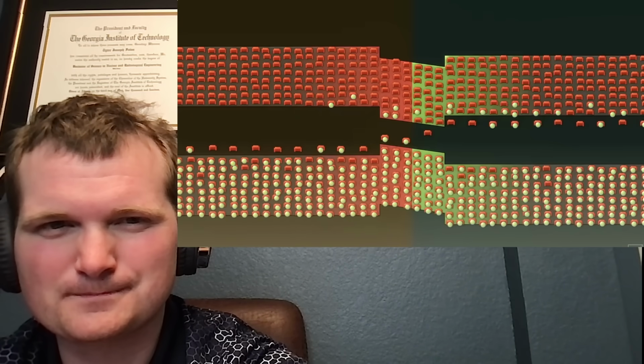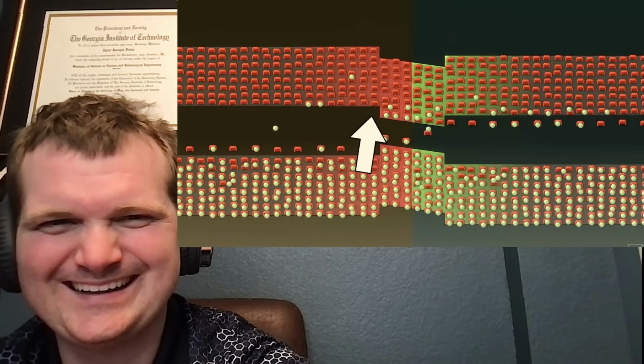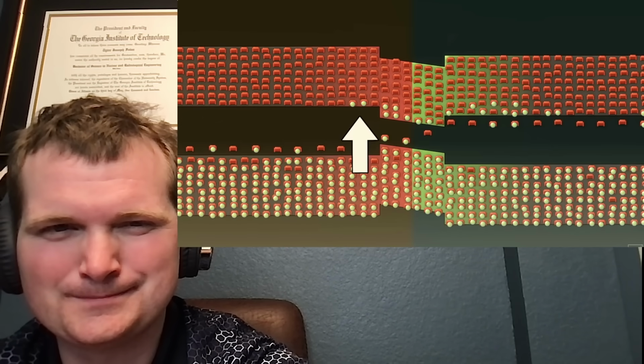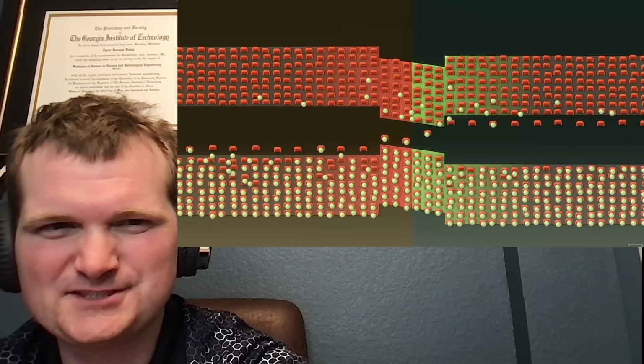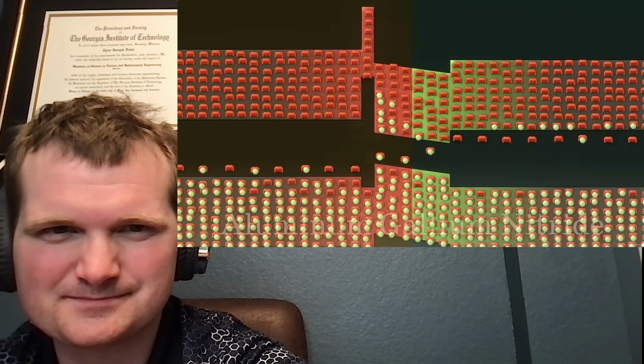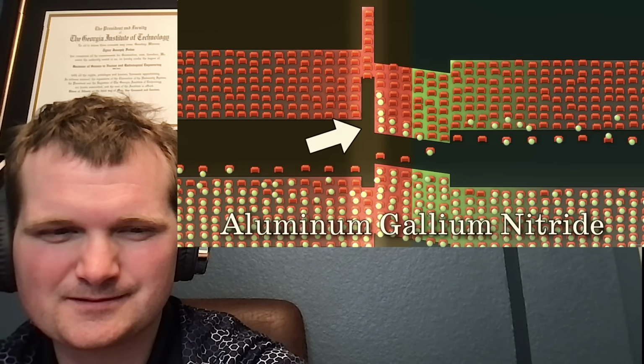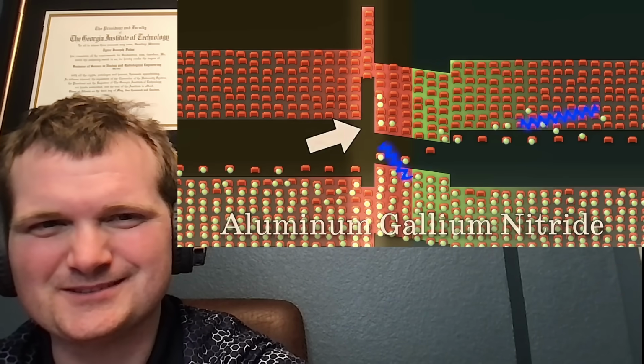To his surprise, the technique worked, giving him a clean indium gallium nitride crystal. He quickly incorporated this active layer into his LED, but the well worked a little too well and overflowed with electrons, leaking them back into the gallium nitride layers. Unfazed, within a few months, Nakamura had fixed this too, by creating the opposite of a well, a hill. He returned to his reactor one more time to make aluminum gallium nitride, a compound with a larger band gap that could block electrons from escaping the well once inside. Oh, that's cool. Use both.